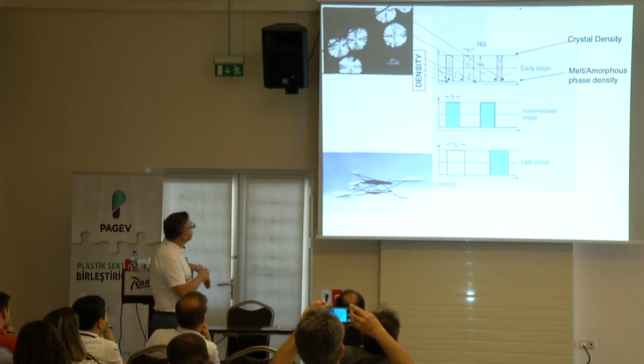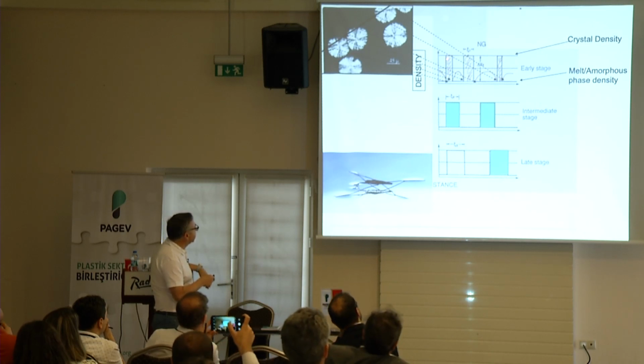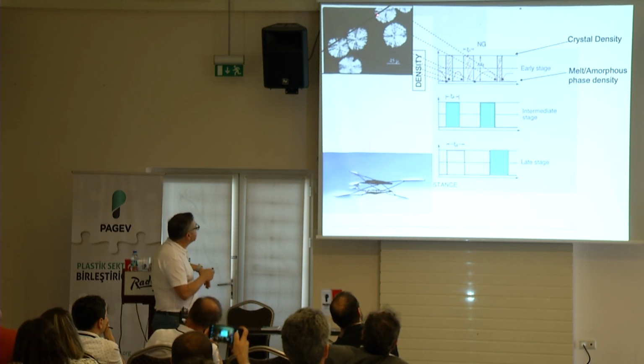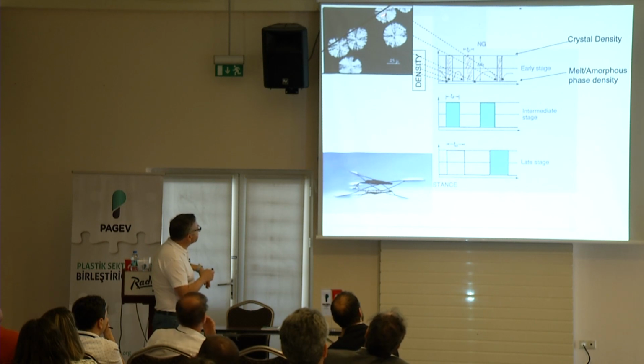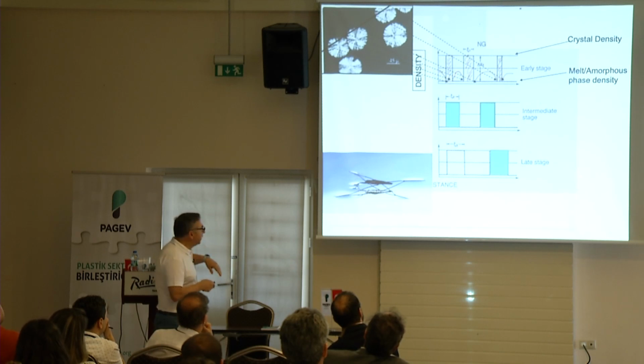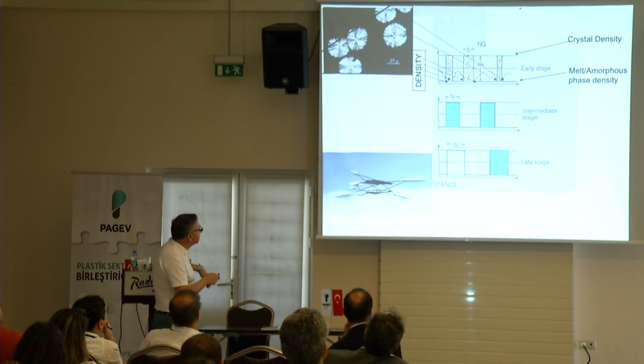So the growth occurs if you draw a line in a spherulite. They typically go to a relatively high density, and just to give you an idea of what happens in the neighborhood of the crystals, there is a concentration gradient. Because the polymer chains are attaching themselves to the crystal, there is a little bit of a concentration gradient near the crystals. And this gives you a sort of downhill effect on the diffusion process. So it gives you an ability to grow the material.